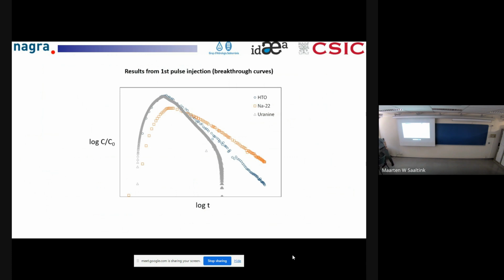Just going to ask what the tailing exponent was for the blue curve. Sorry, what's the tailing exponent that you get? The tail. Is it 3 halves? Yes. Interesting. For the tritium, you get this slope of -2, which is characteristic. In some papers, you see these kinds of values are typical of heterogeneous advection. You have contributions from different fractures and channels inside fractures with different permeabilities and different flow rates. Since they overlap, they end up giving this value of -2. But the interesting thing is that for sodium, you get -1.5. Beautiful, quite interesting.